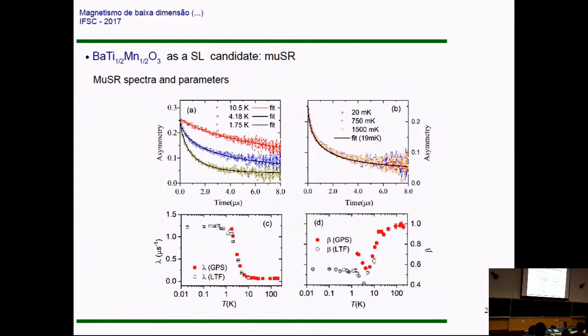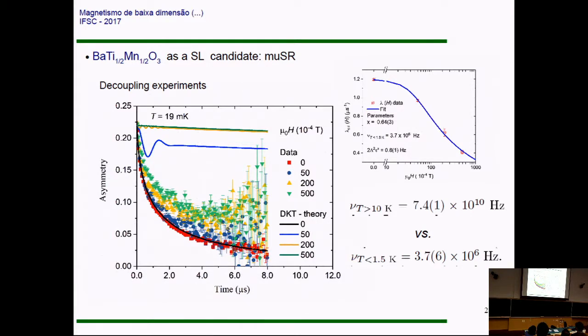The same goes for the extracted exponent. It's about 1 here at high temperature, and then it goes down, but it's really above what you would expect, say 1/3 for a glass state. It's about 0.5 here. Furthermore, we sit at 20 millikelvin and ask: if we have some sort of quasi-static magnetism and we apply a really small field, you would expect to quench this quasi-static fluctuation, and then you would expect something comparable to the theory here. And what you get is that you're still not able to decouple the experiment as we usually talk about.